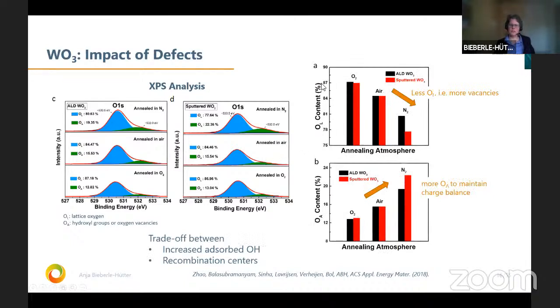So you get less lattice oxygen, so probably more vacancies, when you change the annealing atmosphere from O2 to air to N2, and you have more adsorbed oxygen when you go in this direction. So probably in order to maintain the charge balance at the interface. And what this means is that you have actually a trade-off between increased adsorption of OH and recombination center. So it's a trade-off why the air samples are finally turning out better.